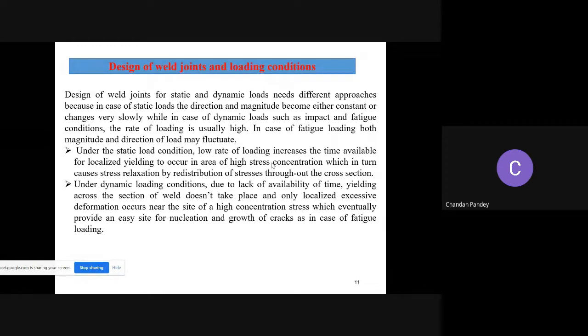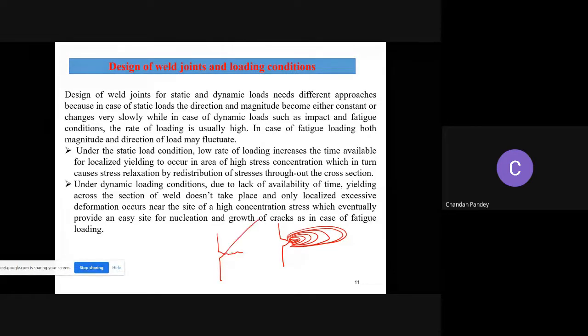Under static loading conditions, a low rate of loading increases the time available for localized yielding. That means in static loading, once a crack initiates, it takes enough time to propagate, because at the tip of it we get plastic deformation. Suppose this one is your static loading, and we get crack initiation at that point. There is plastic deformation at the tip of the crack, and that resists the failure. But in the case of dynamic loading, once a crack initiates, you will get sudden fracture, and generally it takes place at an angle of 45 degrees. So in both cases, we use different approaches to design, and we consider different weld parameters for the static and the dynamic case.